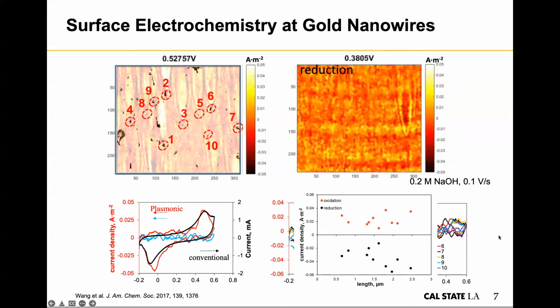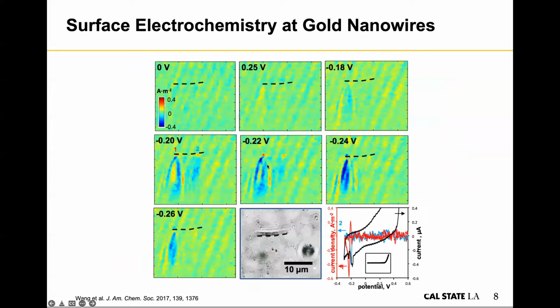Now, we also tried some even longer nanowires. In this case, it's a 10 micrometer nanowire. And with this technique, we can observe that within a single nanowire, at different locations, like at the two ends of the particle, you actually see different electrochemical activities. This could be because the surface facets are different at different positions of the nanowire, or it could be that the capping layer is having an effect there. But in either case, to be able to fully establish the correlation between surface structure and electrochemical activities, we still need to incorporate other techniques to provide more structural information, which is something we're still trying to figure out at this moment.